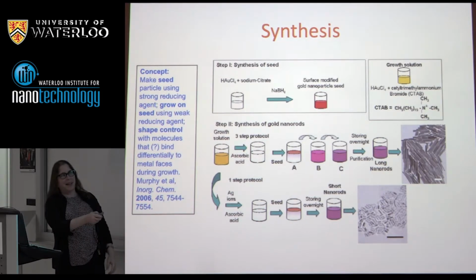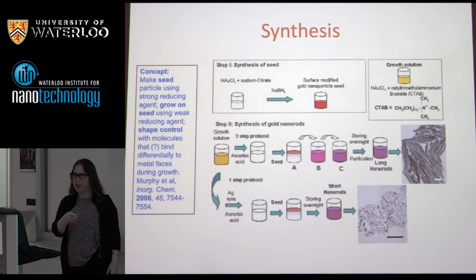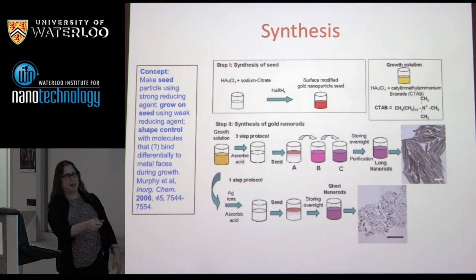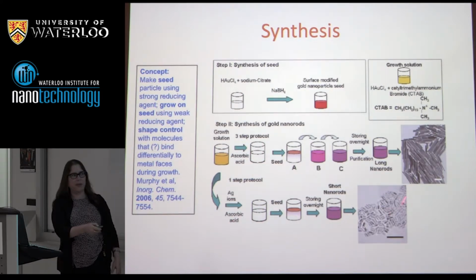Okay, so then, around the same time as other groups, we found that if you add an additive metal ion impurity into the solution, that controls the growth. What's the additive metal impurity? Well, here I'm showing silver nitrate, but it's the same idea. Here's my growth solution. Okay, I have this metal salt, this CTAB stuff. I come in with my weak reducing agent and this other stuff, silver nitrate in this case, and then I add my seeds, and then in one shot, I get a whole bunch of rods.